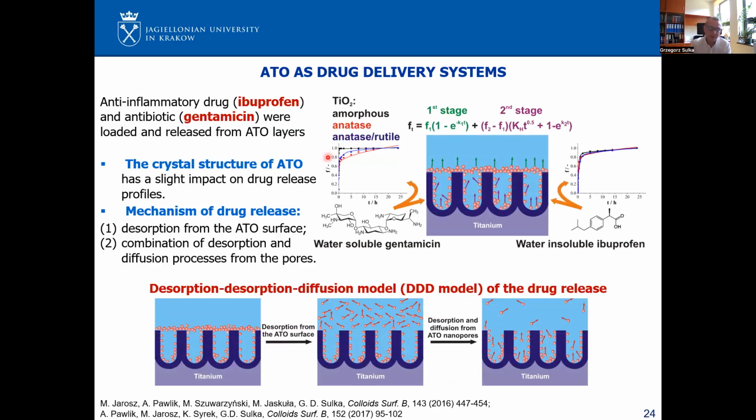There is an example of using such an anodic titanium layer on titanium as a drug delivery system for bio applications. We loaded into those nanopores two drugs, ibuprofen, an anti-inflammatory drug, and also gentamicin, an antibiotic. And we studied the kinetics of release after loading, and we observed two stages of delivery of the drug.